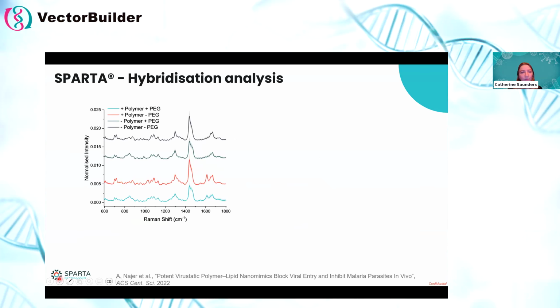So what we looked at was 4 different samples. These were 2 samples containing polymer, the 2 samples on the bottom here, and 2 samples without polymer. What was also compared was the influence of incorporating a PEG polymer, which is for stability. And so this is the sample second from the top and on the bottom.